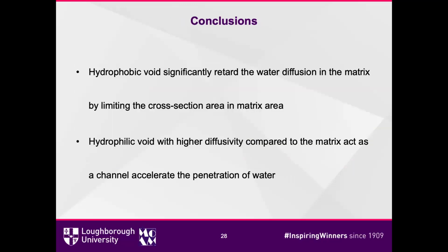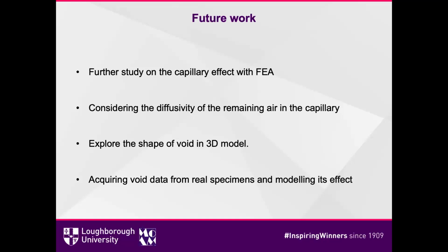So the conclusion is, if we consider whether the void is hydrophobic or hydrophilic, the hydrophilic void has a higher diffusivity compared to the matrix and acts as a channel that accelerates the penetration of water. In future work, I will consider the capillary effect and the hydrophilic void together, and then explore the shape of the void in a 3D model, because previously I did it in 2D. I will also combine it with a real specimen.